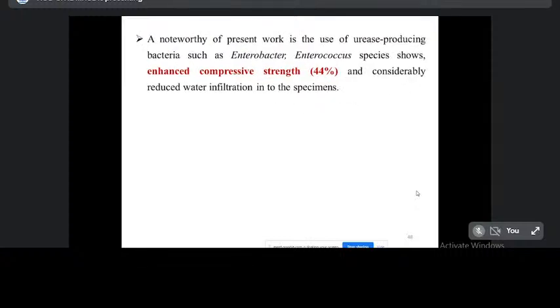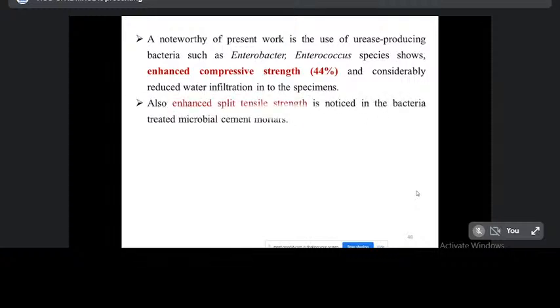Next, we move to the conclusion. From this study, we have concluded the following points. A noteworthy point of the present work is that the use of urease producing bacteria such as Enterobacter and Enterococcus species enhanced compressive strength by up to 44% and considerably reduced water infiltration in the specimen. Also, enhanced split tensile strength is noticed in the bacteria treated microbial cement mortar.